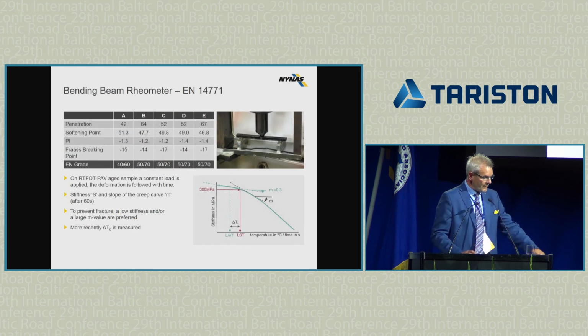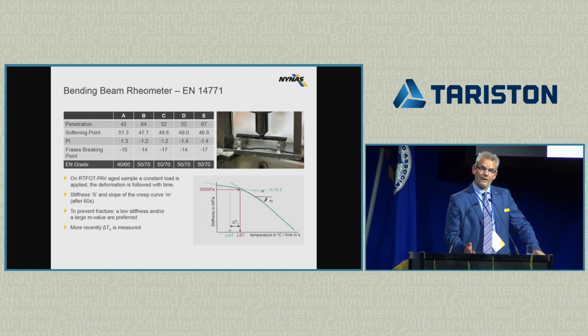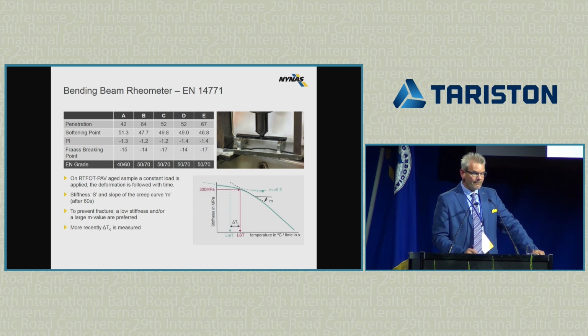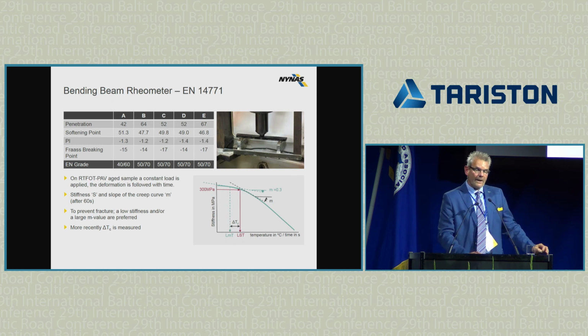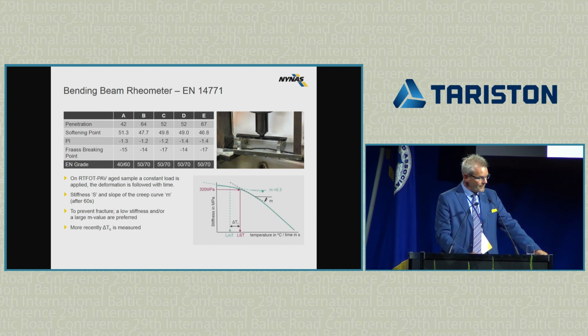Now, how is that relevant for us? Well, in Europe, we don't currently have a bending beam specification for standard grade bitumen or polymer modified bitumen, but we do have a test method. We've taken the test methods from the US to better understand the rheology of bitumen. In this example, we've tested 5 different bitumens, which are quite common bitumens that meet the European specifications, bitumen A to E. They're all roughly, one is a 40-60 grade, the rest is a 50-70 grade. And we've done bending beam tests on these materials.